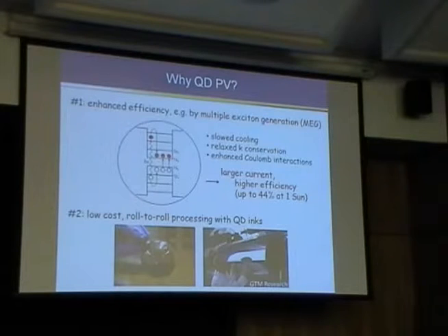The reason these materials might be good for even ultra-high device efficiencies is that they can access some new kinds of physics. For example, multiple exciton generation is something that Matt Beard talked about and Nozik talked about. And this is a phenomenon whereby, if you absorb a high-energy photon, you can, with some probability or efficiency, produce multiple electron-hole pairs across the gap instead of just one. And so we save some of the thermalization losses that are typical in semiconductors. There are a couple of reasons why in quantum dots this process is favored over bulk materials. Matt talked a little bit about that.